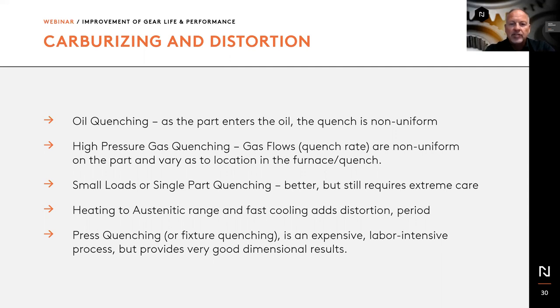Simply, when you heat up to such high temperatures as in carburizing, the austenitic range, the material moves, grows, and distorts, and cooling only will add to this. So a neat process was created called press quenching. Here, a fixture is made to surround the part, a gear, or let's say a bearing race, in order to hold the shape as the material tries to move. This works very well, but it is rather costly. Next slide.